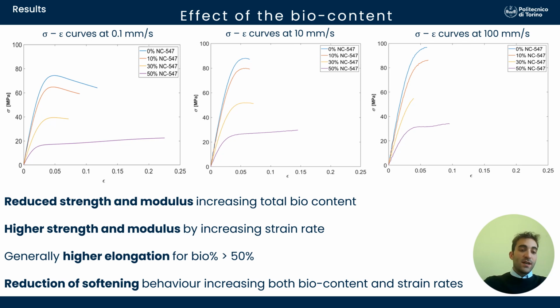Generally, we can see higher elongation for a total bio content higher than 50%, but overall, we can see a reduction of the softening behavior by increasing both bio content and strain rate.